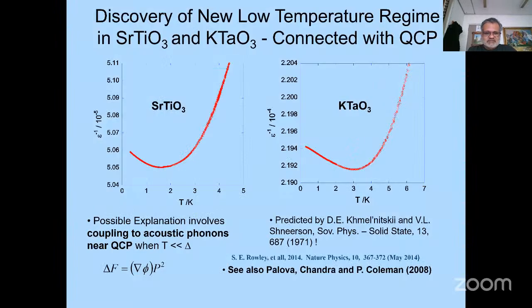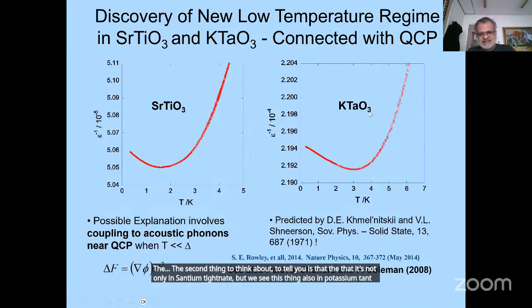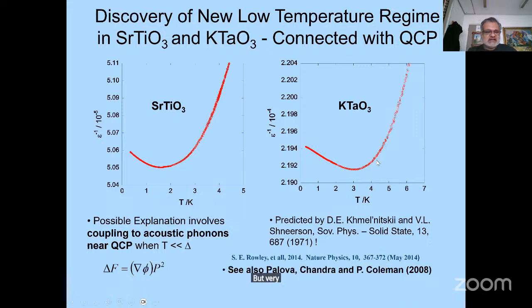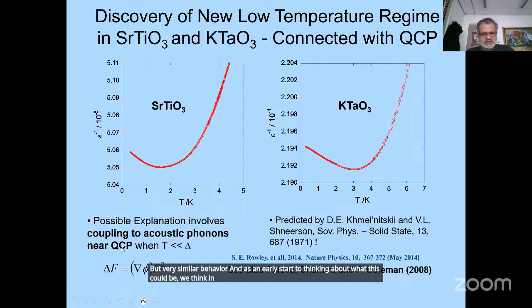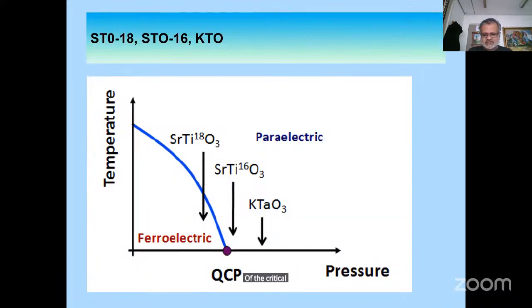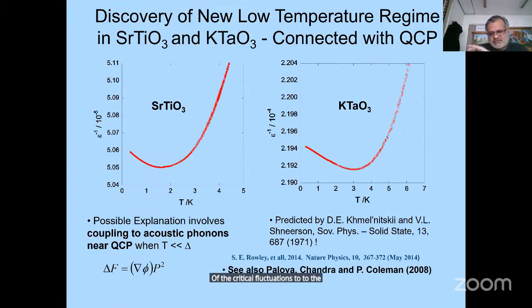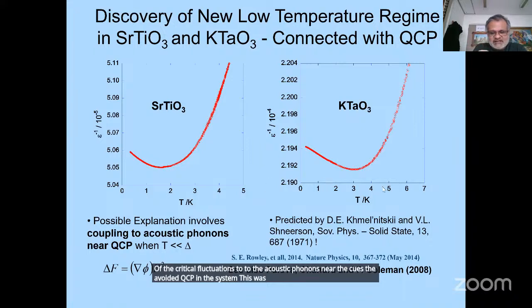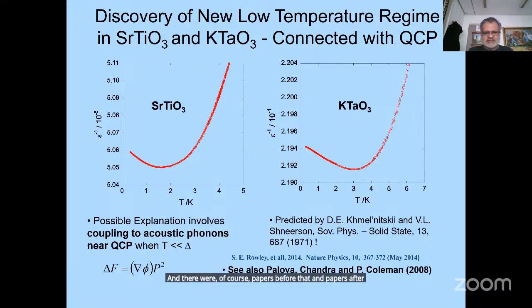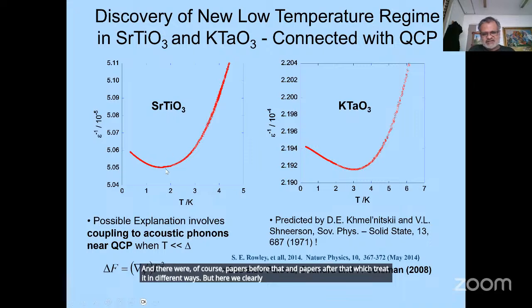The second thing to tell you is that this is not only in strontium titanate, but we see it also in potassium tantalate, at a slightly different temperature but with very similar behavior. As an early start to thinking about what this could be, we think in terms of coupling of the critical fluctuations to the acoustic phonons near the avoided QCP in the system. This was predicted in a 1971 paper by Khmel'nitskii and Shneerson. And there were, of course, papers before and after that which treated it in different ways. But here this 2K, or rather this downturn phenomenon, shows up for the first time.